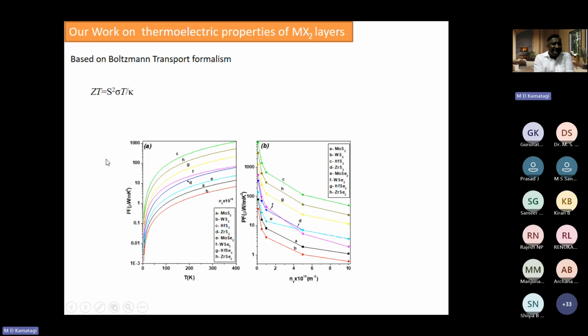What we have seen here is, in the case of MX2 layers, if we increase the concentration of electrons via impurity doping, we should remember it's not straining, then S squared sigma, the product of the square of the thermopower and electrical conductivity, monotonically decreases. Remember, when we dope, the electrical conductivity of these MX2 layers monotonically increases. When we dope, the Fermi energy increases, and this Fermi energy reduces the thermopower. Also, it increases the electrical conductivity. So therefore, the ZT reduces.